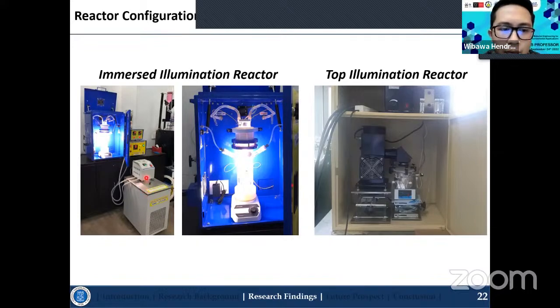So that's why in here we try to balance it by circulating chiller water to the system to keep the operating temperature under ambient conditions. And the second configuration of the reactor, we call it the top illumination reactor, where the light is coming from the top to the bottom of the reactor. So this is the reactor. For this system, it is already configured with a cooling fan. So we don't need to circulate cooling water into the system, because this system already uses the cooling fan to make sure that the temperature is still under ambient conditions.